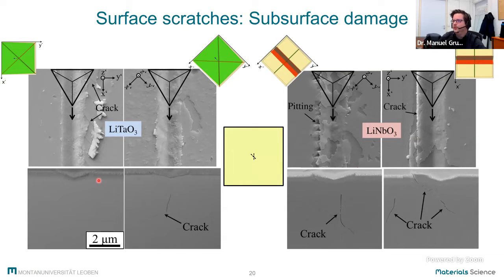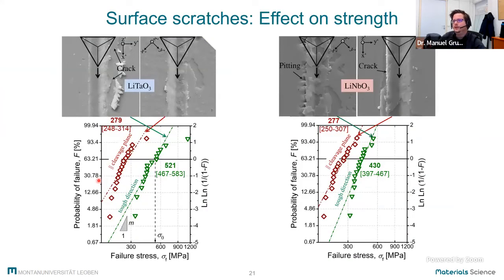We again made the scratches in the center of our specimen, so we were able to test them afterwards in our ball-on-three-ball configuration, and could see that the worst case scenario is lithium niobate with scratches parallel to the cleavage plane. And for other configurations, we get much higher strength values. And especially for lithium tantalate, we can see much higher strength values. The difference in strength we will see on the next slide doing fractography. And then we will have a look onto how this large scatter can happen in the materials.